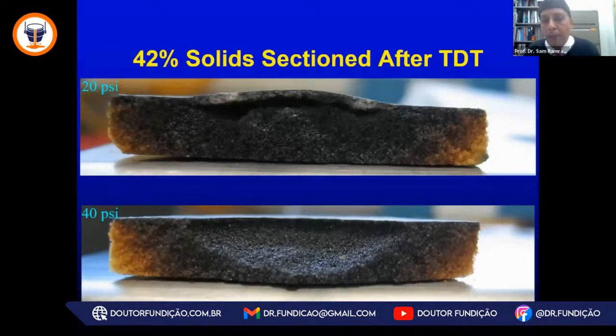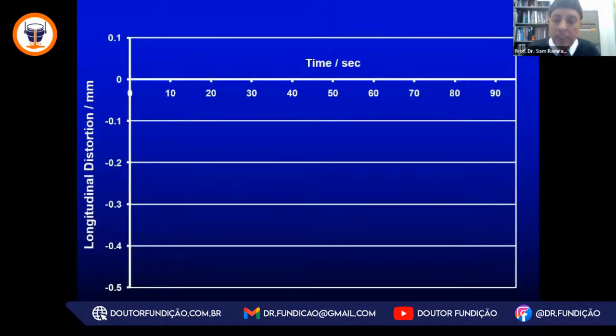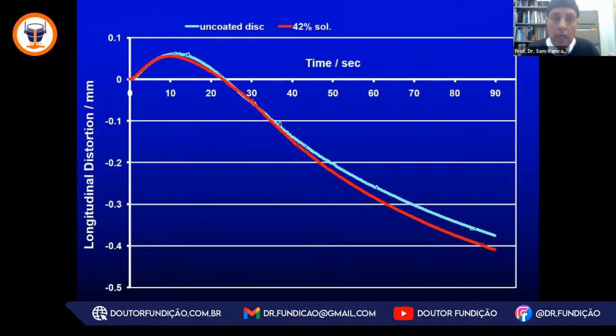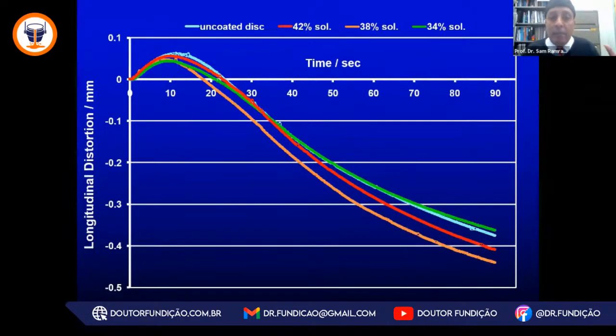But when we apply greater solids, that will give us a proud layer. What you see, if you look at the cross section of the filled specimen, versus the lower levels of solid, you see a delamination. You see the mold wall dilate. It's the gas from the chemical binder system delaminating against the coating layer. And that is going to cause distortion as well. All of these problems can be depicted from an uncoated and a coated specimen at higher binder levels.